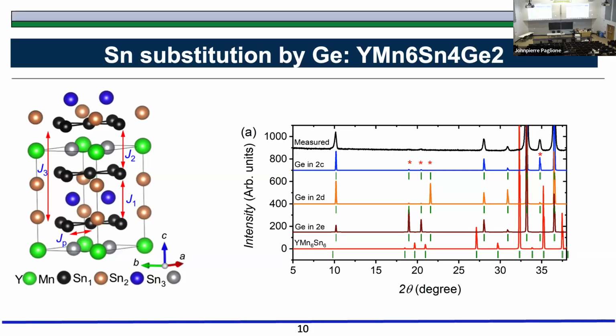But there is one thing that I have still not discussed with you, is that in this material, the most important or interesting aspect is the interaction of these spins from layer to layer. Within one layer, these manganese atoms are strongly interacting with one another, so they are a ferromagnet. But these manganese moment here, they can talk to the manganese moment here, and this interaction is labeled as J1. This is exchange interaction. Then, likewise, this manganese layer can also talk to this layer, and this is not same as this because of its structure.